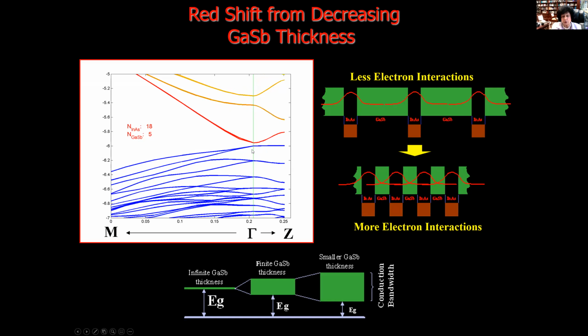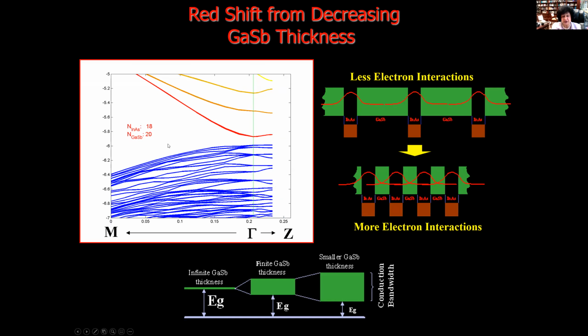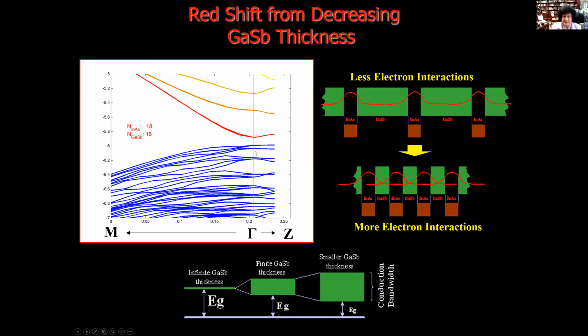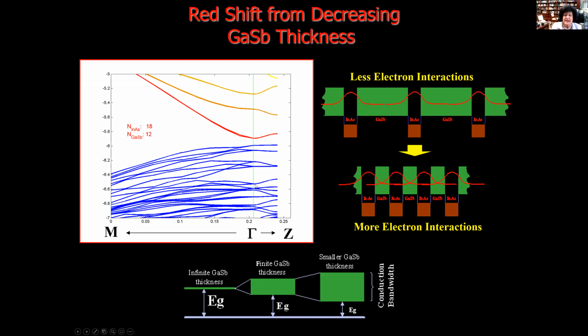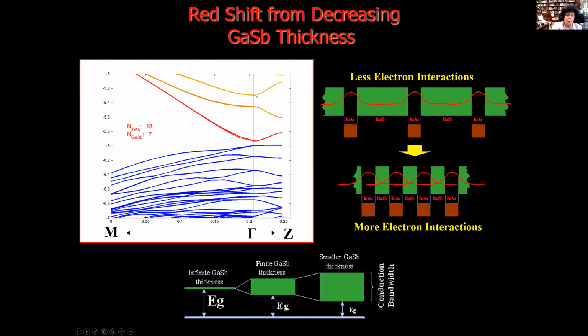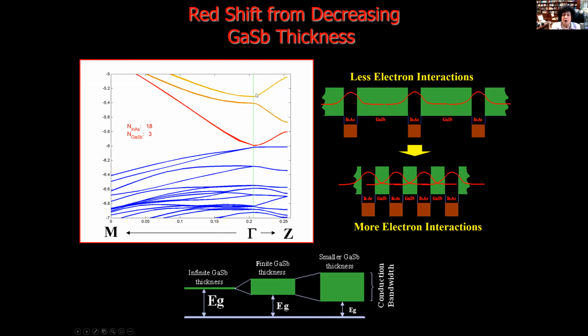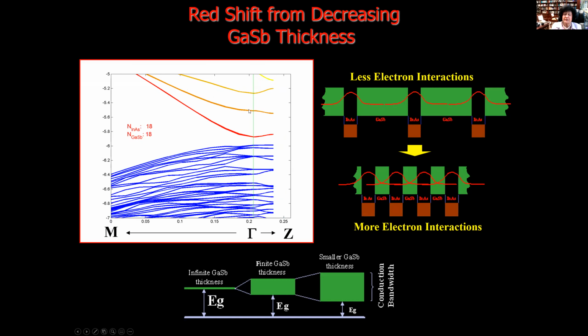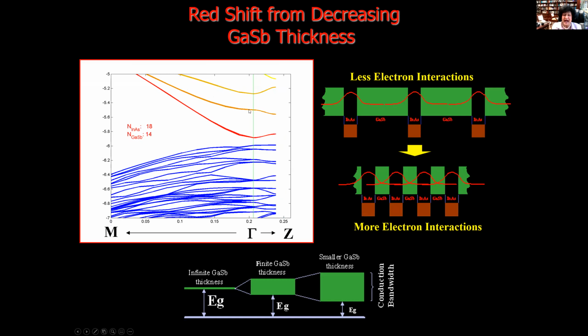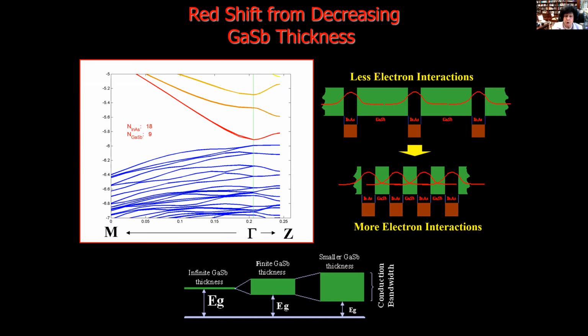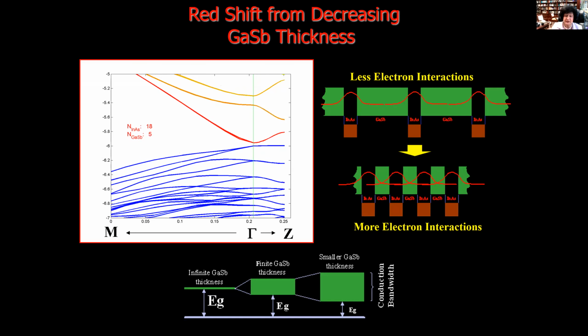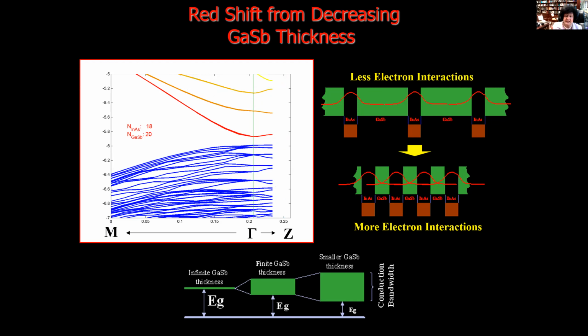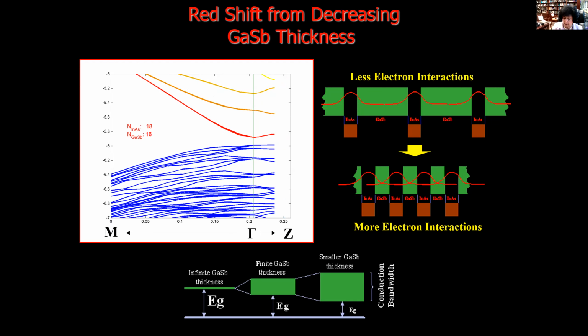As you can see, not only with a 1-2 monolayer chain can we change the gap, but at the same time we can change the inter-gap, the interband, and eliminate Auger, as an example, and have all of the best. For the same wavelength, we have many different ways to optimize the structure, as opposed to mercury cadmium telluride, where for any wavelength we have only one possibility.